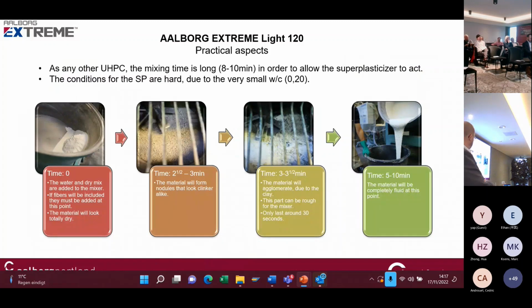And practically, it is also a strange material to mix. You can almost not compare it to a traditional concrete. The consistency is very different. That is because when you start with the dry powder and you start mixing with adding the water, you first see that you have nodules appearing, and these nodules are becoming from a small diameter to a larger diameter, and they come after 3 minutes approximately in a clay phase, because of the agglomeration of the big nodules, which becomes very hard to mix at that moment. It is for about 30 seconds that it is very hard for the mixer to go through this phase, and then after 5 to 10 minutes you have self-compacting consistency ready to cast.